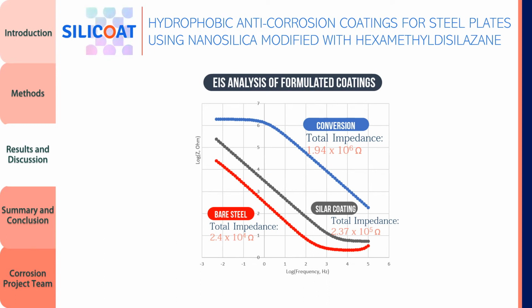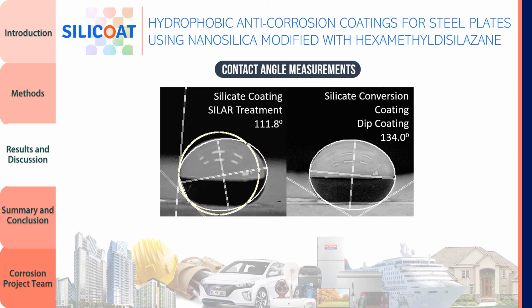Another way to present the impedance performance is to look at the resulting Bode plot. From the plot, impedances from the optimum formula both for SILAR and conversion coating showed higher performance compared to bare steel. Conversion coating shows even higher impedances by 2 orders in magnitude at the low frequency region. Both optimum coating formulations developed using SILAR and conversion coating were found to be hydrophobic, as shown by the high contact angles, higher than 90 degrees.